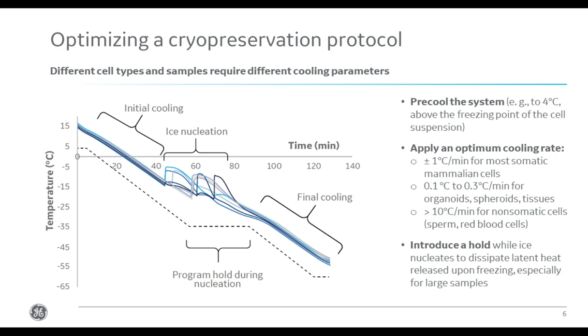You might also have come across some protocols that have something called an ice nucleation plunge step to start the ice formation process. Typically, we would not recommend these as they've never really been shown to be effective. However, for large volumes, say vials or bags greater than around 20 mL fill, having a hold around -30 or -35 degrees to allow for bulk ice formation is also common, and that's shown in the thermal profile presented in this slide, corresponding to a freezing of 8 cryobags filled with about 70 mL each. This hold gives time for the large latent heat of fusion of ice to be dissipated.